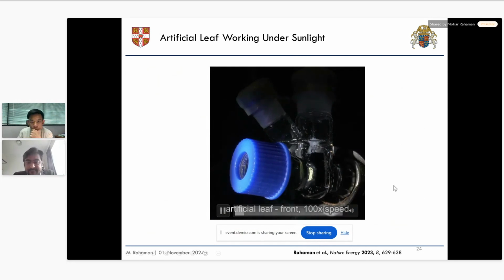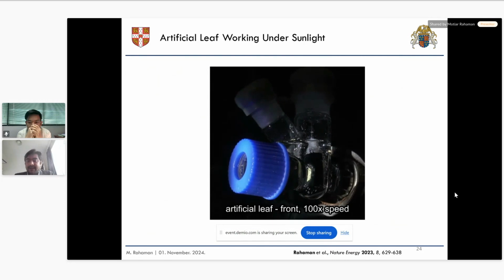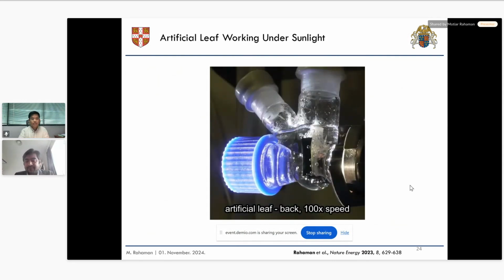It's coming out. Of course, this is 100 times increased speed. It is not the real speed shown here, but we can see some nice oxygen evolution from the photoanode side while shining light, and it will flip. On the other side, we can see also some hydrocarbon and hydrogen evolution from the photocathode side. So we just shine light on the standalone device, and it works without connecting to anything. This is the photocathode side now, and we can see the bubble formation with time.